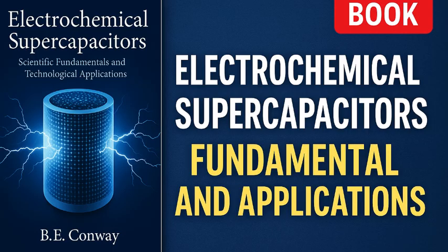Conway noted power densities of existing capacitors being well above those of nickel cadmium or lead acid batteries. Nickel cadmium might deliver maybe 200 watts per kilogram, and electrochemical capacitors can do several kilowatts per kilogram easily. In fact, that 30 kilowatt per kilogram example we gave is extreme but illustrates the point. One interesting nuance: because the capacitor's voltage drops linearly with discharge, if you want to use the energy between 2.7 and 1.3 volts effectively, you may need DC to DC converters to maintain steady output.